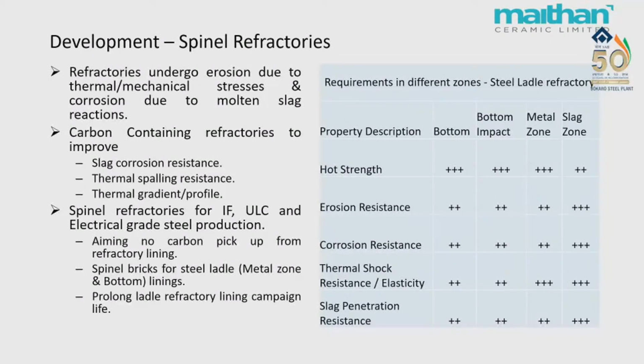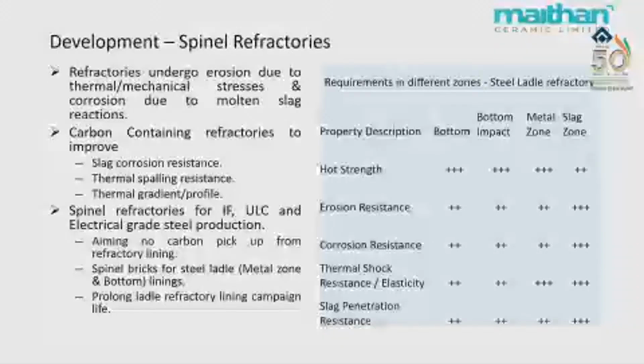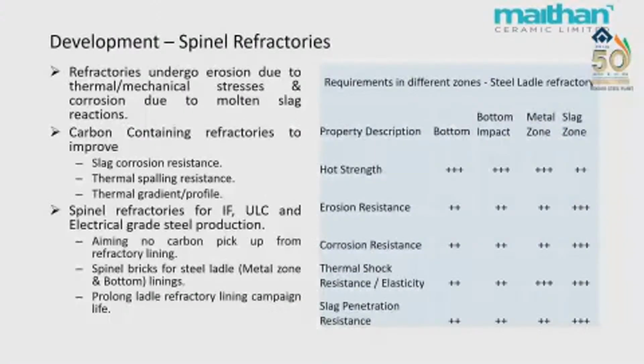Talking about the spinel bricks, the main properties we are looking into are erosion resistance, corrosion resistance, thermal resistance, that is a kind of elasticity, and the slag penetration resistance. So based on this, mainly the steel ladle refractories were designed with carbon containing refractories, basically magnesia carbon. Magnesia carbon containing refractories basically form the linings.